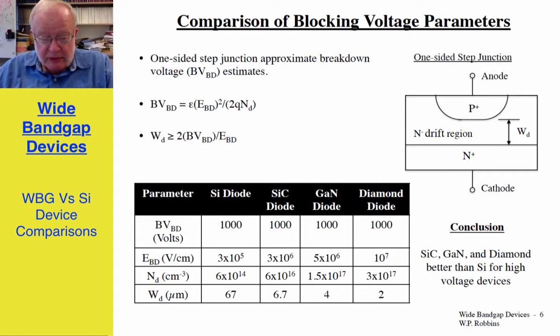And if you look at the table here, I'm assuming equal breakdown voltages for all 4 types of materials. And what we see is doping density in silicon has to be quite small, 6 times 10 to the 14th. The other materials can be a couple orders of magnitude higher, which means significantly lower on-state losses. The width of the drift region, or length if you like, is pretty long in silicon, 67 microns. All of the others are at least an order of magnitude smaller, with the smallest being in diamond. Smaller drift region lengths, of course, also mean smaller on-state losses.